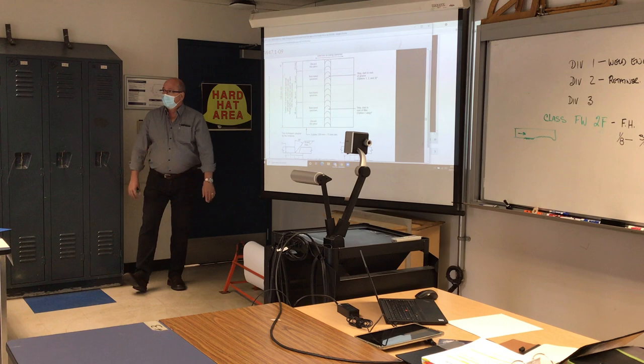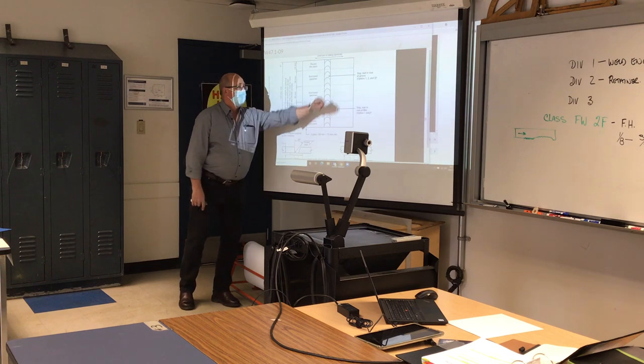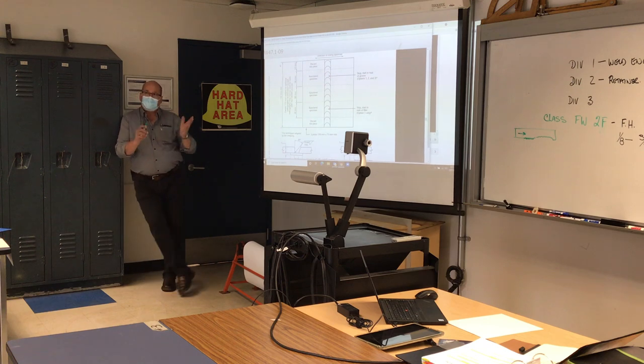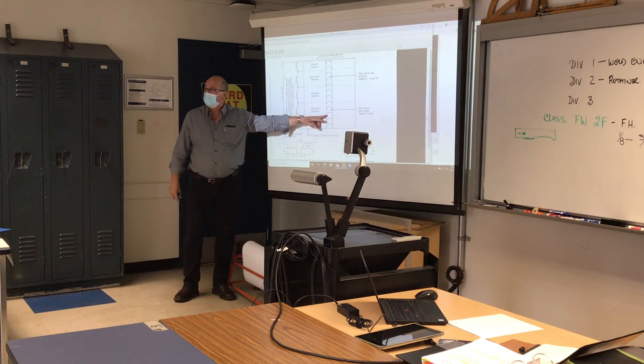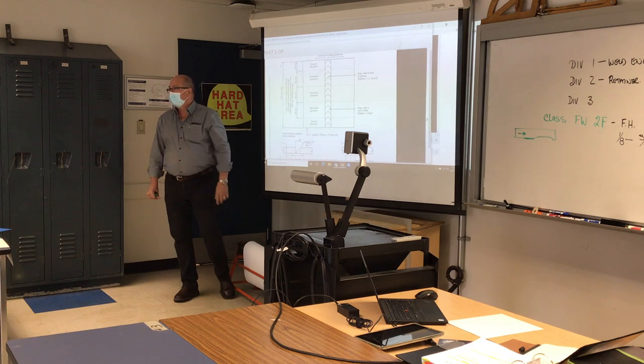Or we'll get it machined. And we're going to cut it to length, and then I want you to cut 3 strips out of it. Little strips here, 1.25 inches, 1.5 inches, thereabouts. But what's really important is I need those radiused just a little bit on the edges, and you cannot make them any thinner than they were to start. So you can't grind this thing down so it's 1/8 thick in the middle here and hand that in. It's not going to work for you. Okay?